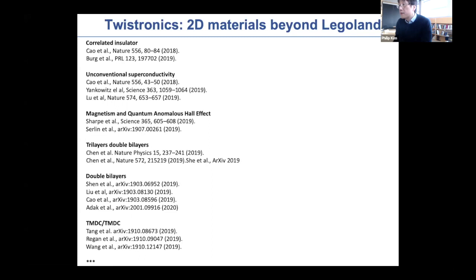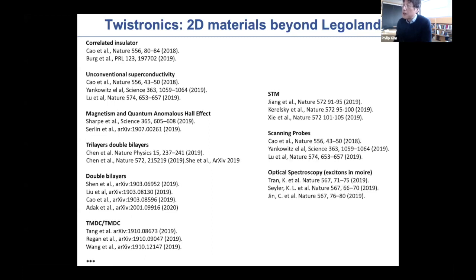other experimental tools, especially scanning probes, can be readily accessible. So there have already been a couple of STM works showing interesting electronic structures in coordination with the atomic registries in the magic angle twisted bilayer or close to it. A couple of STM works as well as scanning probe works show local compressibility measurements, as well as a local field dependence measurement by a scanning SQUID, showing the electronic and magnetic properties locally. I think this type of trend will go on, especially since this local property plays quite an important role.